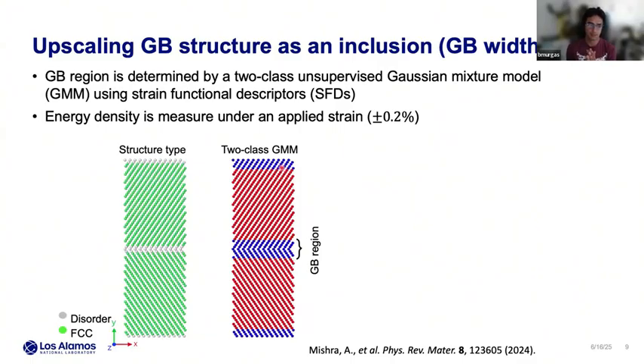The main difference is that when you use a classical method, or one that is already built into OVITO or something like that, for this grain boundary you will have this kind of grain boundary region here in white. But if you use this Gaussian mixture model, you will have a different grain boundary region. They have shown in this paper that this model works pretty well, and they also compared it with several cases for polycrystals and different things. The main difference is that we use strain functional descriptors, and that is what really makes the difference between the two models.